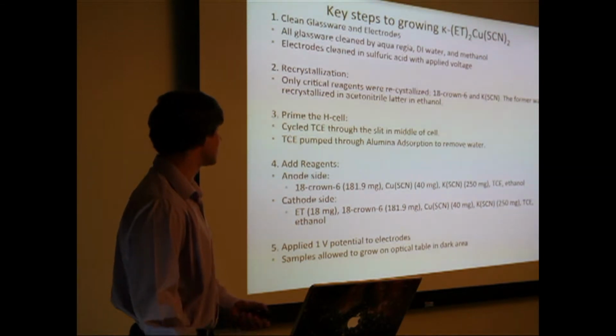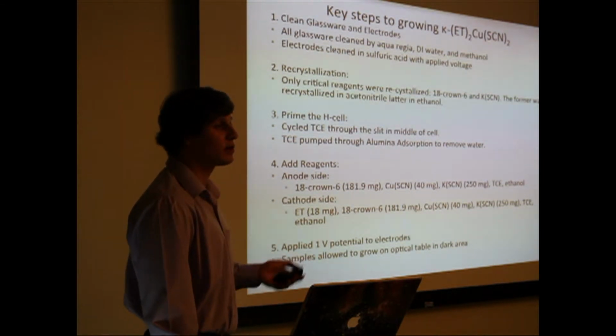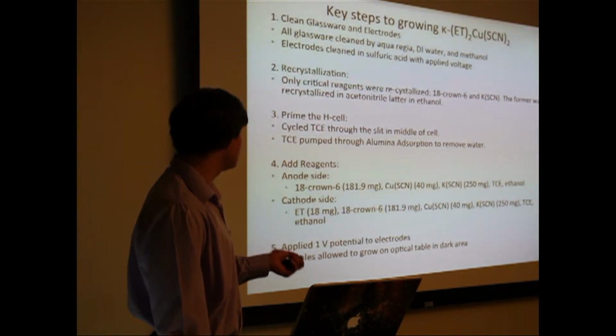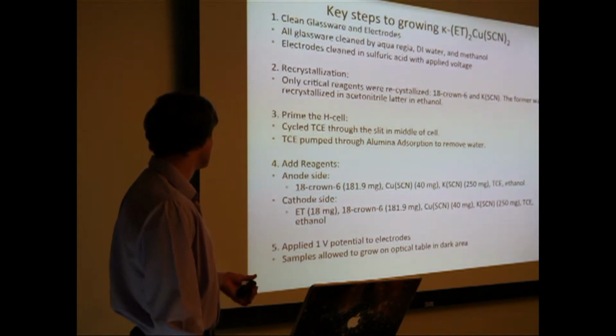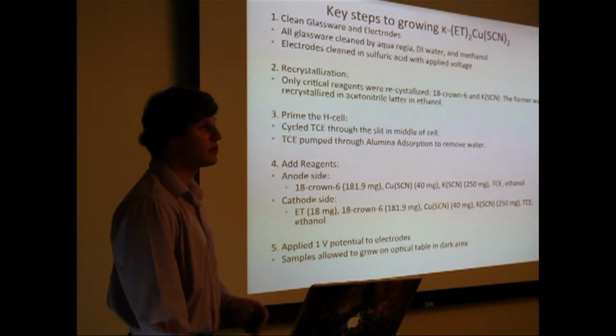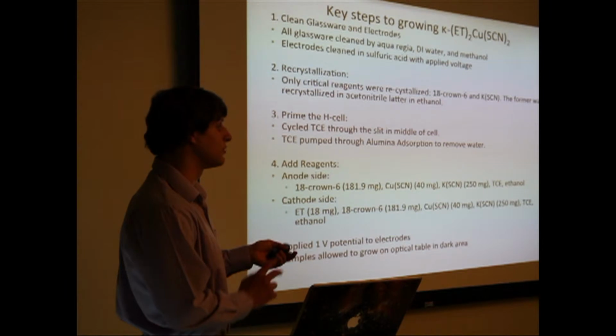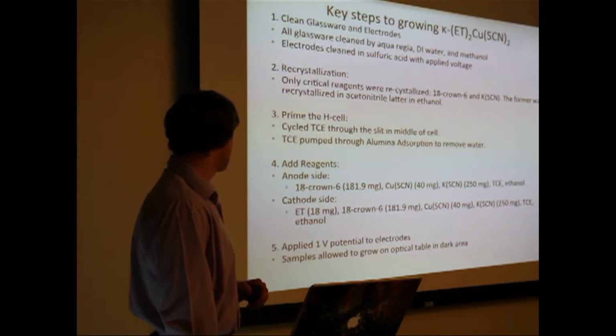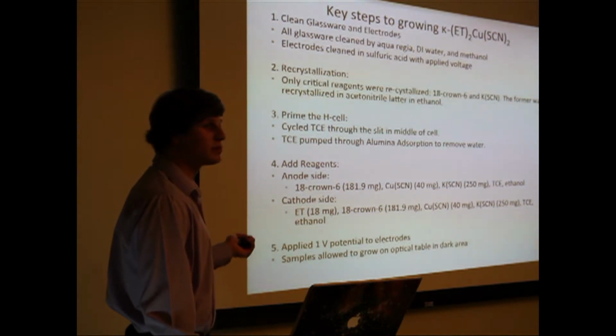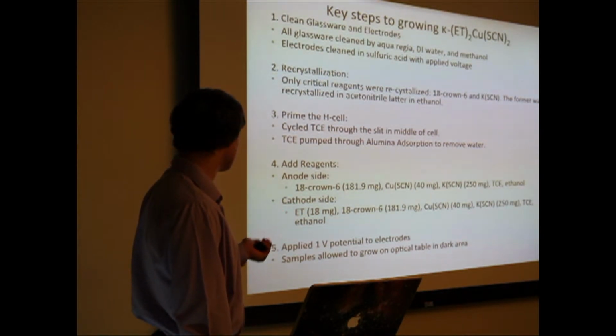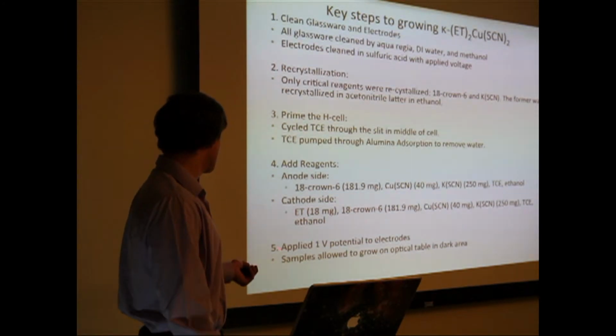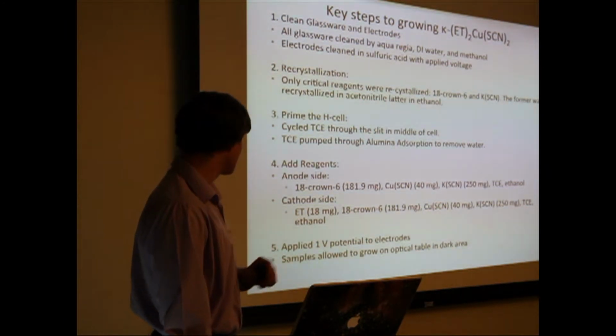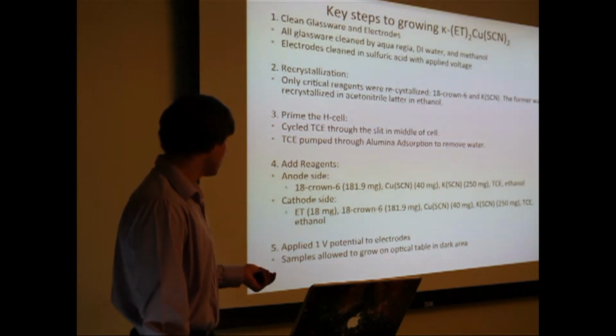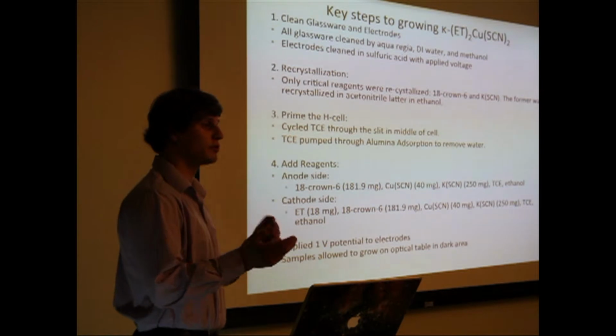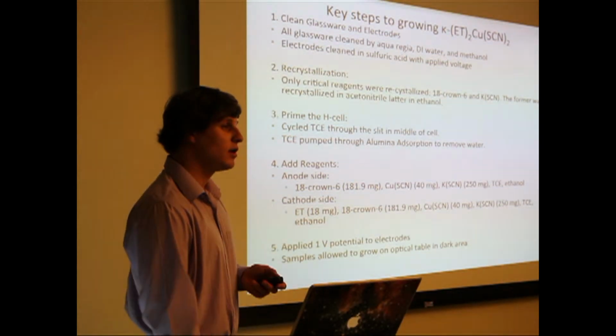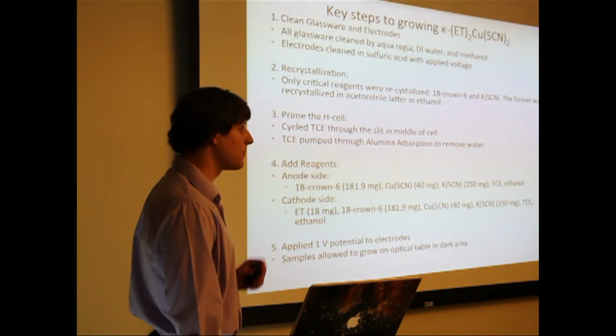On the anode side, which is the negative side of the electrode, we added 18-crown-6, copper thiocyanate, potassium thiocyanate, TCE, and ethanol. On the cathode side, we added ET, 18-crown-6, copper thiocyanate, potassium thiocyanate, and everything else, TCE and ethanol. This is because on the cathode side is where the reaction actually takes place. ET is the biggest contributor to the molecule, so we wanted that on the cathode side. After that, we applied 1 volt potential to the electrodes, and we let them grow in a dark area on the optical table. The optical table was so we can prevent most of the vibrations, because the crystals are very sensitive, and they're also very sensitive to ultraviolet light, hence the dark area.